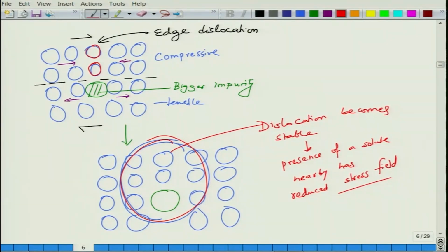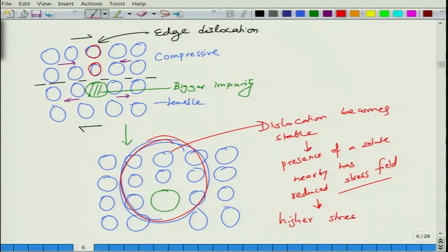So, this is basically what we call solid solution strengthening, where we can see that the stress required to move the dislocation has increased because the impurity reduces the stress field around the dislocation by compensating the stresses. So, earlier you had tensile stresses, when you put in this bigger impurity it introduces compressive stresses, as a result the stresses become lower and hence the dislocation does not feel the need to move out of the crystal. So, basically you require higher stress to move the dislocation further. So, this is called solid solution strengthening. It can happen by virtue of putting substitutional impurity atoms as well as interstitial impurity atoms.